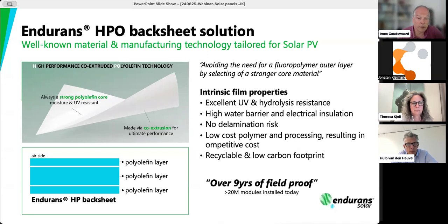The performance fulfills all the requirements, so it even has a better water barrier compared to polyester, which is also related to the chemical characteristics of the polyolefin. Because we do not laminate, but co-extrude the three layers from the melt, they adhere very well, and there's no delamination risk. And polyolefins are the cheapest polymers you can use, so also cost-wise, there's not much of a difference compared to the polyester base. And we already have 9 years of proof in the field, so our bankability is increasing by the year. Next slide.